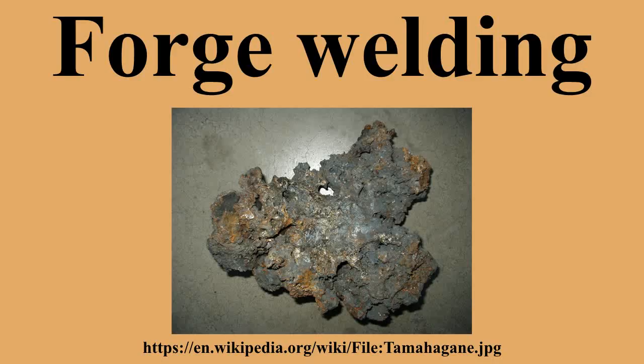The first welding process was forge welding, which started when humans learned to smelt iron from iron ore, most likely in Anatolia around 1800 BC. Ancient people could not create temperatures high enough to melt iron fully, so the bloomery process that was used for smelting iron produced a lump of iron grains sintered together, small amounts of steel, slag, and other impurities, referred to as sponge iron because of its porosity.